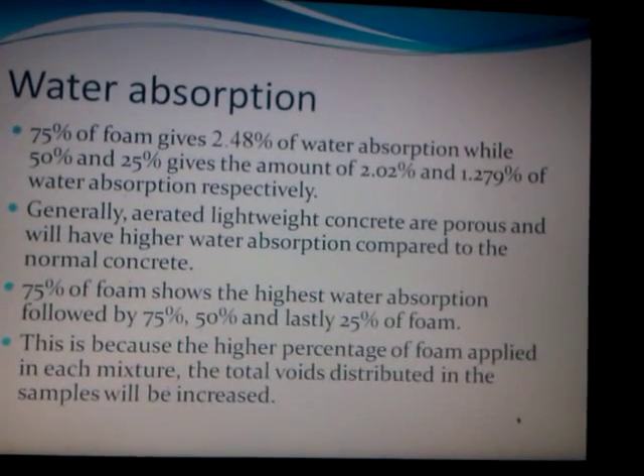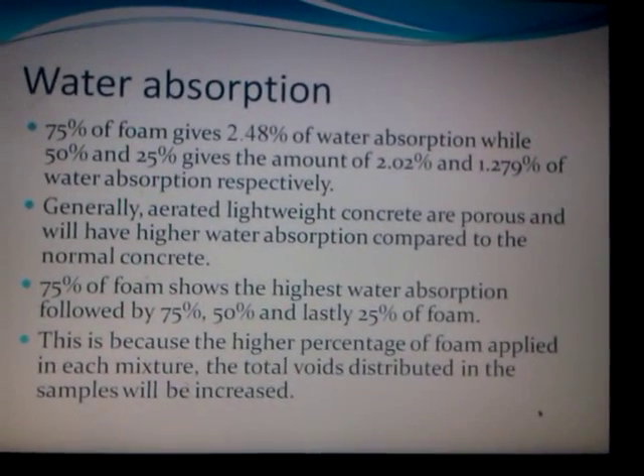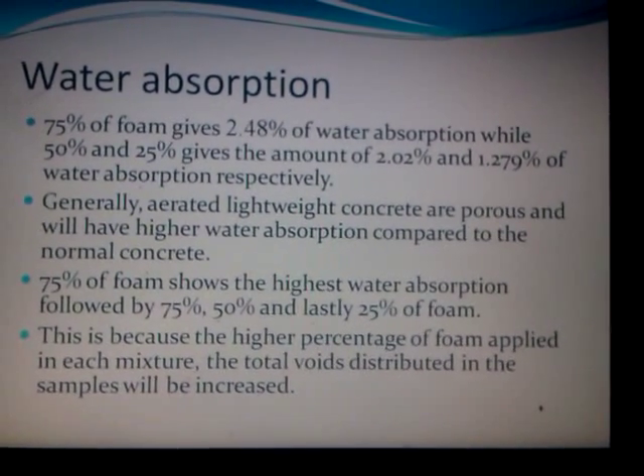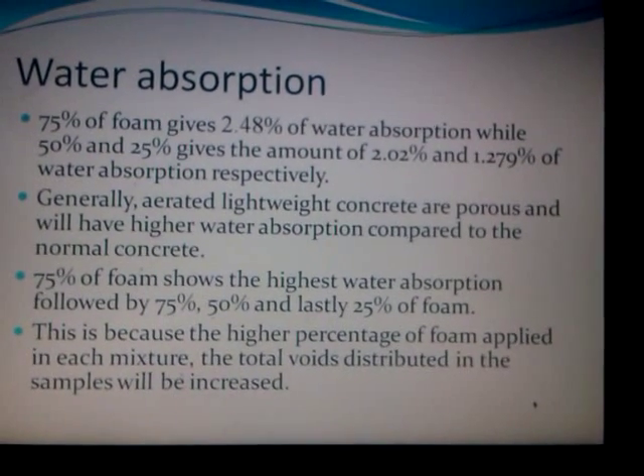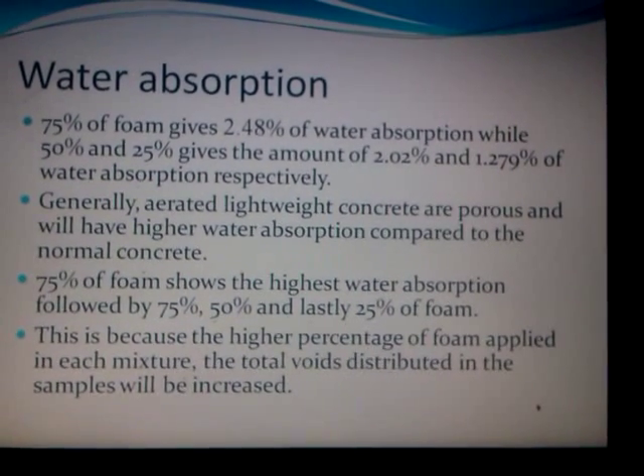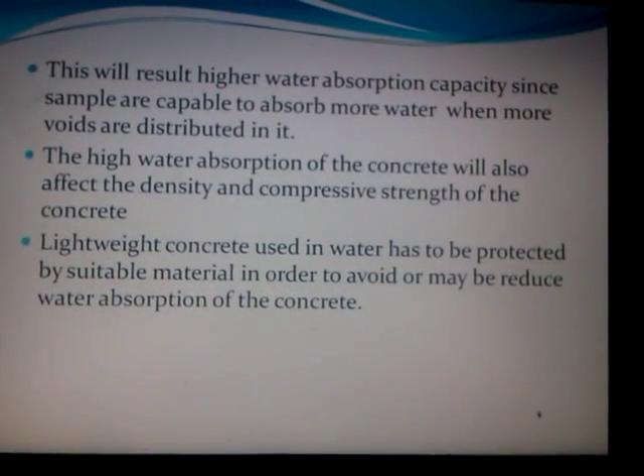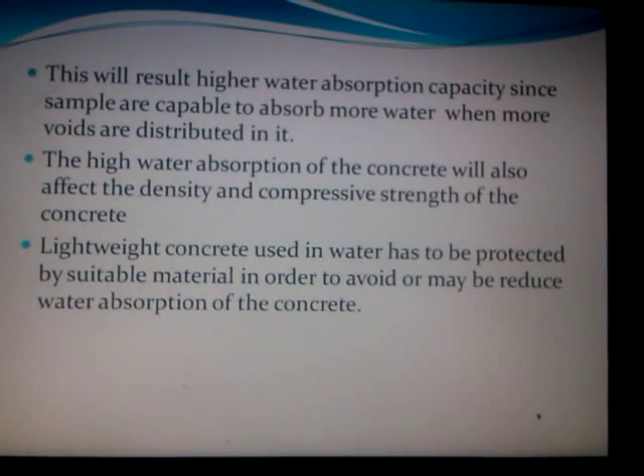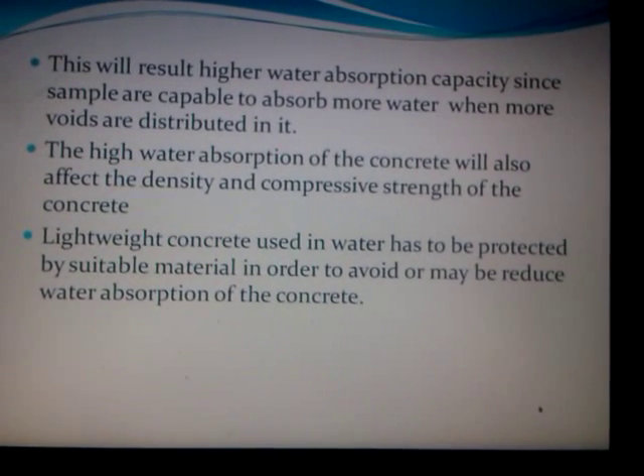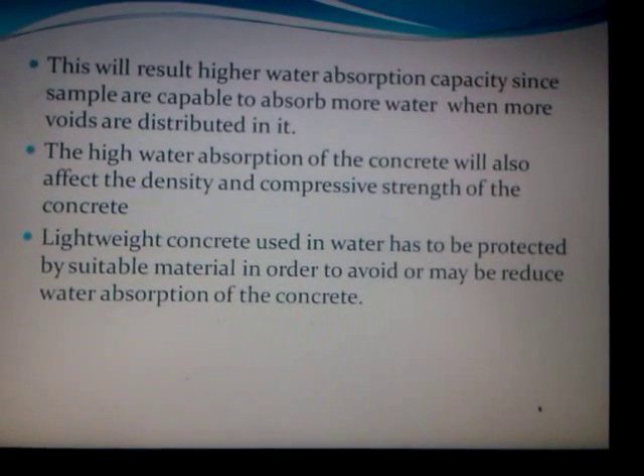Regarding water absorption: the 75% foam gives 2.48% water absorption, while 25% foam gives 1.279%, which is smaller. Generally, lightweight concrete, being porous, has higher water absorption compared to normal concrete. 75% foam gives the highest water absorption due to the presence of a large number of voids and porosity, resulting in higher absorption capacity. Lightweight concrete used in water exposure must be protected by suitable materials to reduce water absorption.